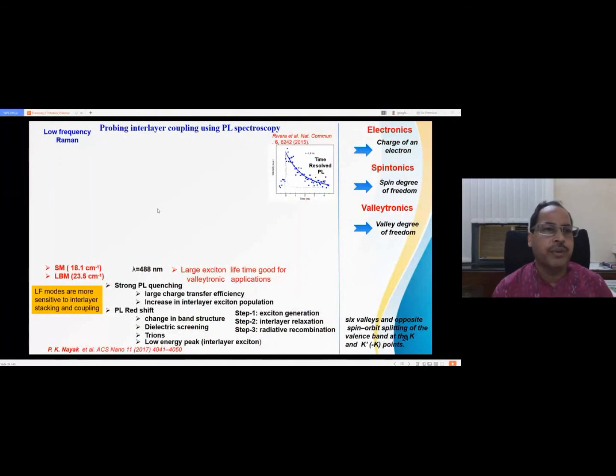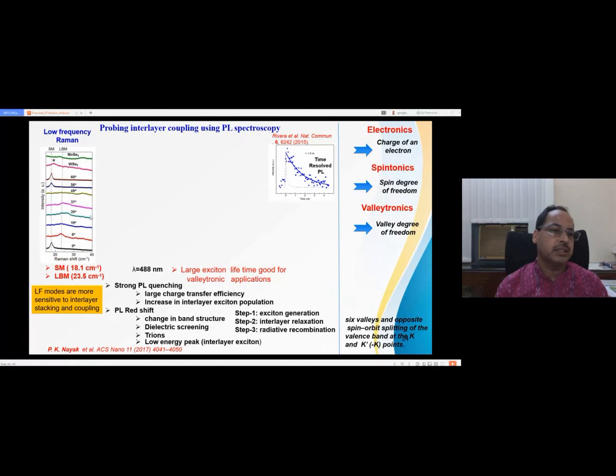So now you see the low frequency Raman mode. We have done it for the low frequency as well as the high frequency Raman mode. In case you can see when the stacking is very symmetric, like 0 and close to 60 degree, we can see a shear mode, and at other angles you can get the layer breathing mode, LBM mode. But this low frequency mode is more sensitive to the interlayer stacking and coupling. So people are mostly exploring this.